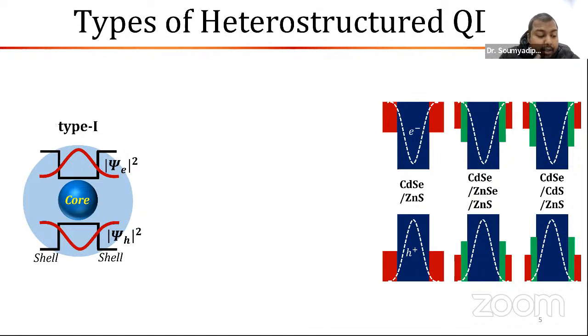For CdS, they expand the conduction band efficiently, and the extent of increase of the quantum yield is not as much as with zinc sulfide or zinc selenide. So you can see sometimes people put both zinc sulfide and zinc selenide shells to obstruct the exciton leakage and basically extend the valence band range.